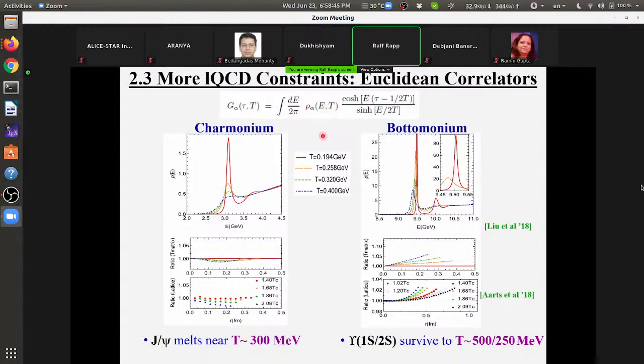However, if you have a spectral function from, say, a model calculation, then it's very easy to check how it compares to Euclidean correlators. And this is what is shown here. So for the bottomonium, for various temperatures, the resulting spectral function here for the strongly coupled scenario can be used to calculate these correlator ratios relative to some reference correlator in the denominator. And you find a reasonably good, I would say, semi-quantitative agreement with this piece of lattice data as well.